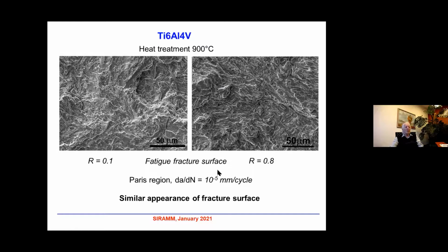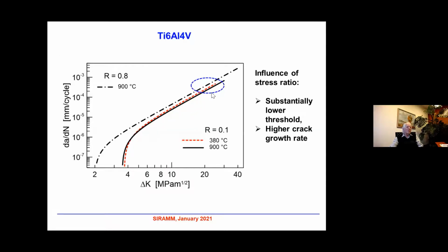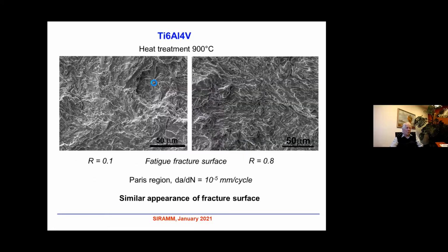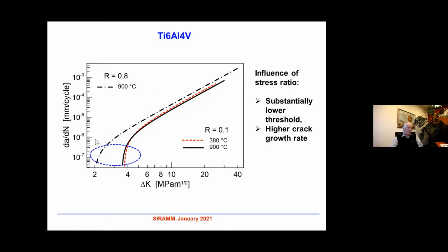So in the Paris region, for these high rates, the fracture surface is practically similar, and it means that the crack growth mechanism is practically the same in both cases, whether the mean stress is high or not. What about the threshold region here, where the influence of R ratio is so strong?